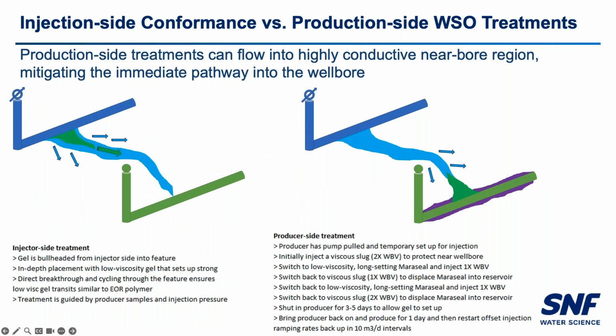So just in terms of the difference, an injection side treatment, we're bullheading the gel into these features that exist. This is just showing a schematic for a horizontal system. Again, we're playing off the initial viscosity and the gel kinetics to allow us to have in-depth placement, starting with a low viscosity gel. A lot of times we're seeing breakthroughs from the injection well to the producer well on the order of hours. So we need varying grades of gel to fill that.